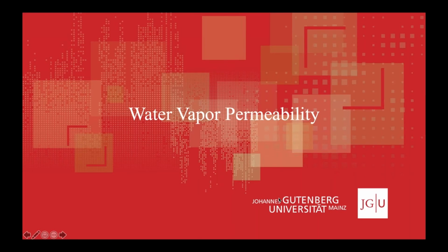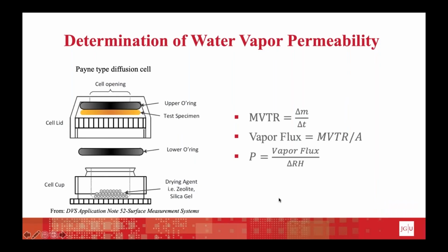Okay, so at last we can also protect, of course, our formulation with the right choice of packaging material. So we assess the water vapor permeability of some packaging materials. This can be done using a Payne-type diffusion cell, which consists of a small lower cup where we can put a drying agent inside. For example, we use the silica gel. And between two O-rings, we can put then our test specimen and close this with the cell upper lid.